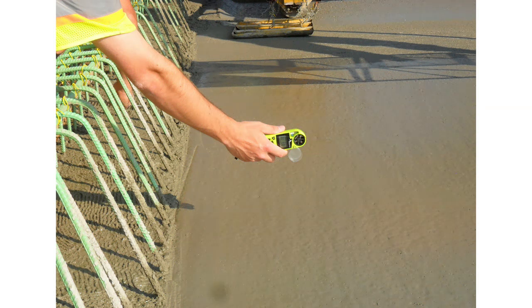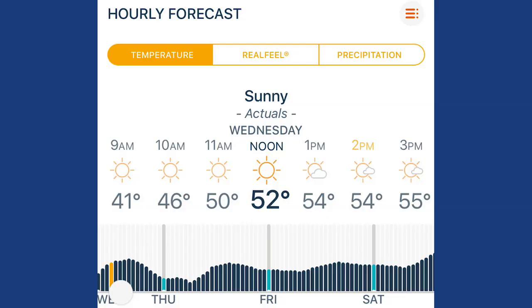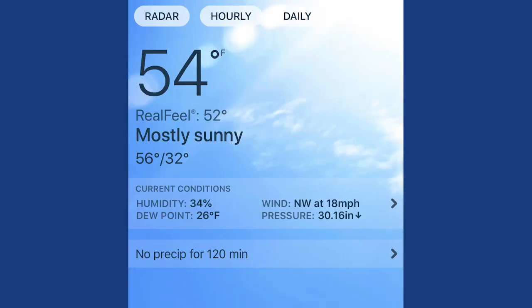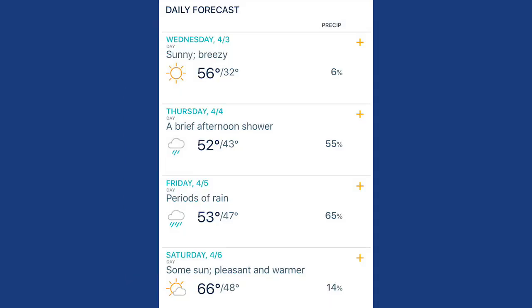Ambient conditions during bridge deck placement, as per Publication 408, Section 1001.3. Do not proceed with mixing and placement operations if the forecasted ambient temperature is expected to reach 80 degrees Fahrenheit within the scheduled placement time, or if the evaporation rate will exceed 0.06 pounds per square foot per hour. Unless otherwise authorized in writing by the department, do not start the deck placement operation until the ambient air temperature is a minimum of 40 degrees Fahrenheit and rising, and is predicted to stay above 40 degrees Fahrenheit throughout the entire deck placement operation.